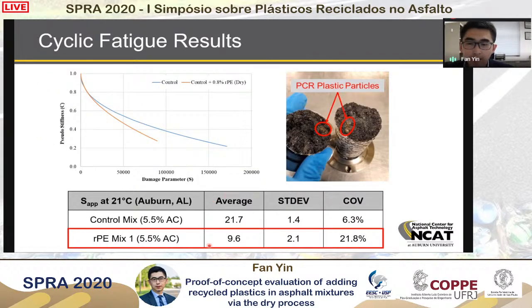Now getting into the results, when we look at the index parameter, we can see very consistently that with the recycled plastics added, the mix has a much lower Sapp number, which indicates reduced fatigue resistance. And we saw the same trend when we look at the pseudo stiffness versus damage. If we look at any given damage and we draw the line here, the one with the plastic has a much lower pseudo stiffness as compared to the control mix, which agrees with the Sapp number indicating reduced fatigue resistance. And very interestingly, our engineer working in the lab running the test showed me this picture. As we can see here, there are some plastic particles that we can identify just based on visual observation at the cross-section at the failure point within the specimen. So it definitely affects the behavior of these mixes when we run the test.